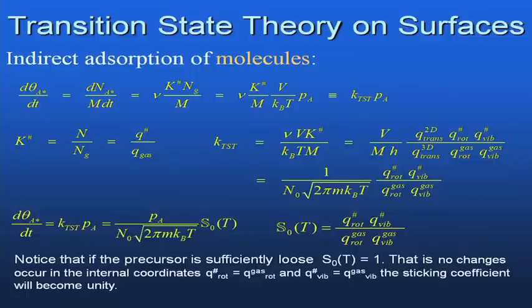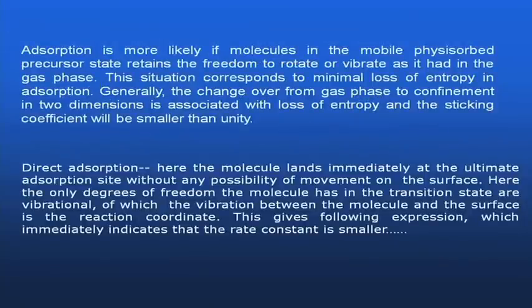Okay. So, for your loose precursor, if the precursor is loosely bound, then the situation is like this. Adsorption is more likely if molecules are in the mobile physisorbed precursor state, and retain the freedom to rotate and vibrate as they had in the gas phase. This situation corresponds to a minimal loss of entropy in the adsorption process.